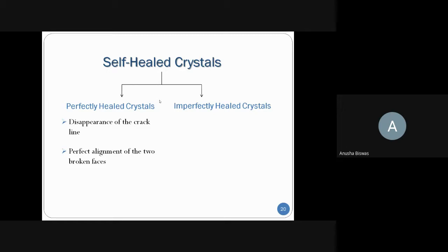Now, in the case of the imperfectly healed crystal, if the fragments are reassembled in such a way that their crack lines are visible and the healed crystal behaves like two crystallographic units, these are called imperfectly healed crystals. Actually, the crack line is visible here and misalignment of the fragments has taken place. But as it's healed, it still can hold its own weight when it's lifted by one part.